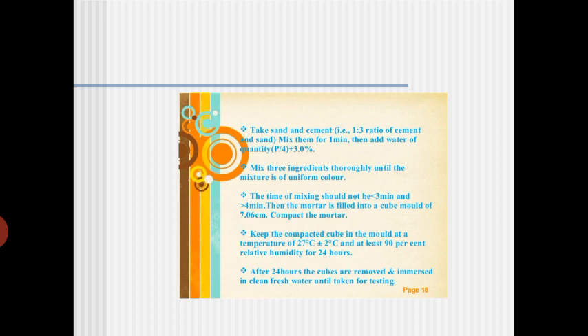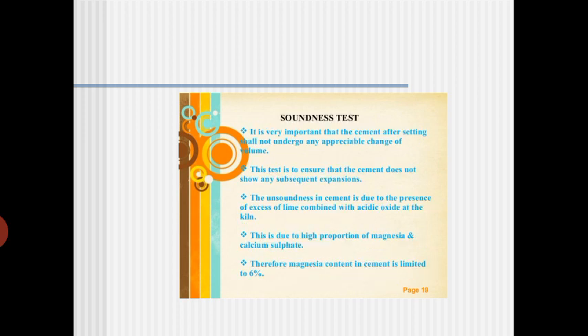Then the mortar is filled into a cube mold of 7.06 centimeter height. Then compact the mortar. You have to compact it. Then keep the compacted cube in the mold at a temperature of 27 plus or minus 2 degrees centigrade and at least 90% relative humidity for 24 hours. After 24 hours, the cubes are removed and immersed in clean fresh water until taken for testing.